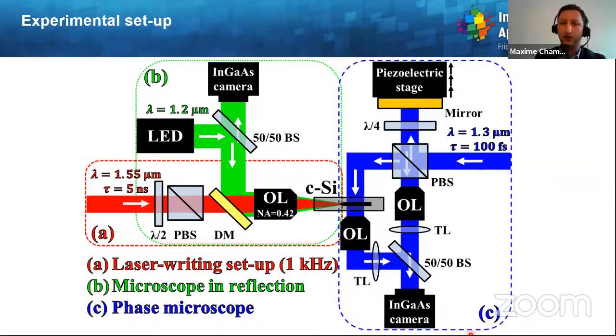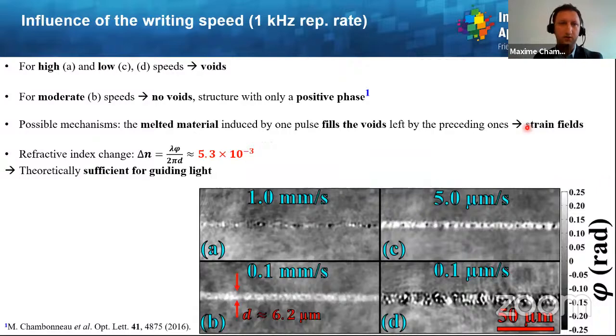And besides, we have another diagnostic, which is represented here, which is nothing else than a Mach-Zehnder interferometer, which is transposed to the infrared at 1.3 micron wavelength, and it allows us to have phase images. So what is the phase shift of the laser-induced modifications, which are essentially related to the refractive index change. Then here are some typical results we obtain when one tries to inscribe some lines inside the material at different scanning speeds, so different feed speeds.